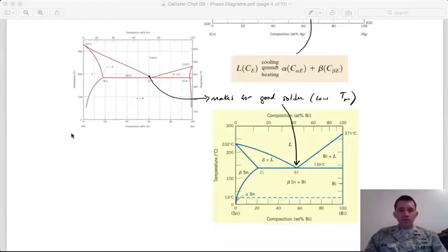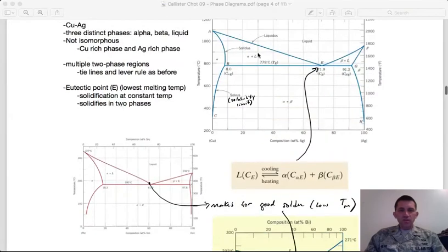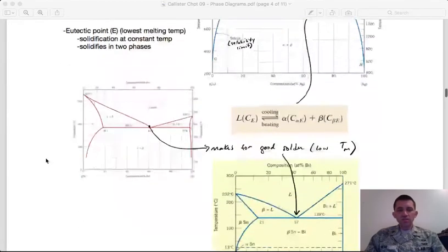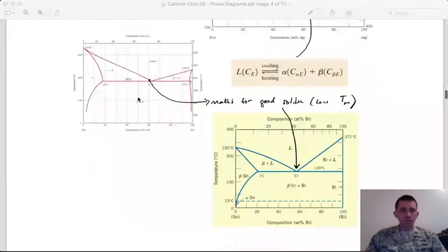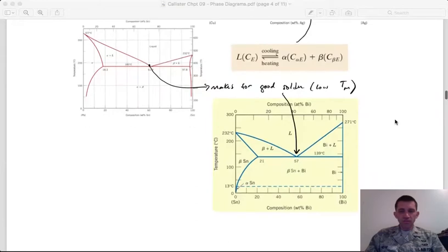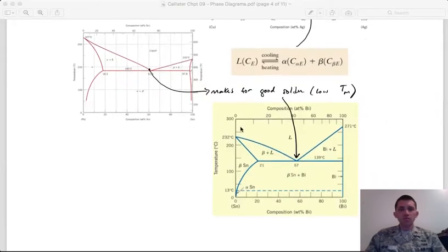The other thing to notice is that generally the eutectic point is the lowest melting point of any composition. And so eutectic composition is often used for applications that require a low melting point metal. One example that comes to mind is solder for making electrical connections. You'll notice here, this is more of a legacy material, but we have lead-tin solder. This was used for many years as the solder material of choice.